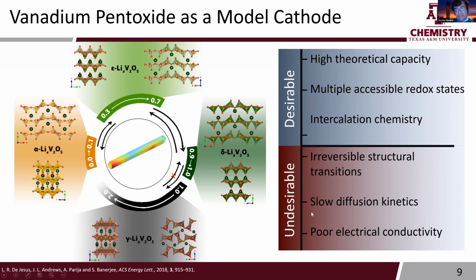The diffusion kinetics can slow down, especially for these highly lithiated structures, and the electrical conductivity is not great because of the large band gap in this material. So these are all issues that we need to resolve, and I think our ability to both control atomistic structure through design of different polymorphs, as well as to understand how to control particle morphologies in this system, provide a real good handle for understanding some of these multi-scale interactions that are at play here.